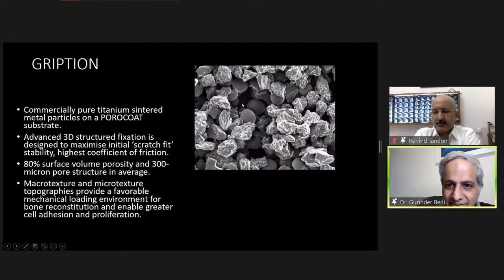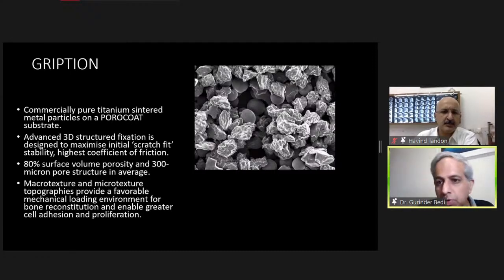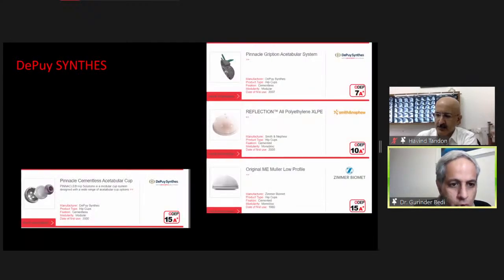So this has got the POROCOAT technology, plus you have these sintered particles on top of that. So this was titanium, this is also titanium. Again, it's a surface coating which they've actually produced on it. We produce a high degree of roughness, better bonding, whether macro or micro.